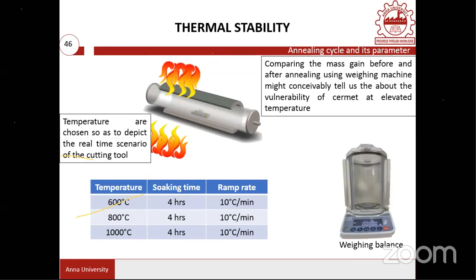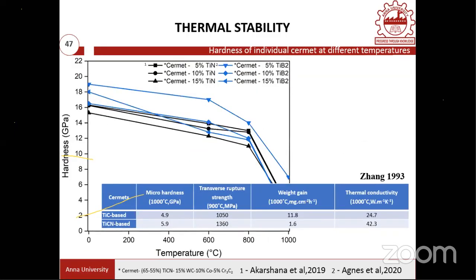So one can say what is the temperature domain within which the mechanical properties are stable. Therefore, that is the temperature range which is recommended for the operation. So beyond that, if you work on the material, probably you may lead to some catastrophic failure due to various phenomena like new phase formation, or probably grain coarsening or something like that. So we have conducted this thermal stability study for these 3 temperatures, keeping this constant soaking time. And if you look at this, we have taken only TiB2 and TiN based compositions, and keeping this cobalt constant.